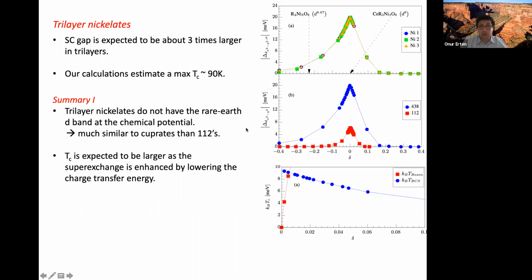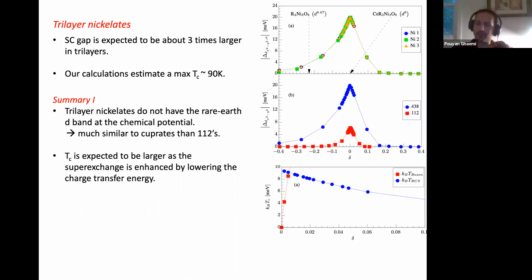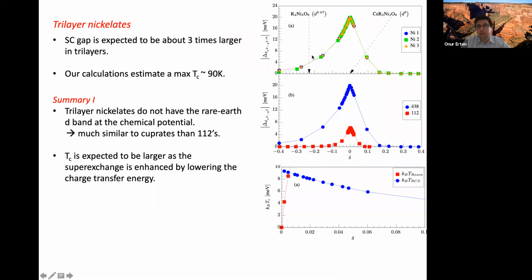Any questions? So the tight binding model, you directly do it for the 3-layer, right? Yes. Okay. Because I was thinking that if this is really getting to the cuprates, can you integrate out some bands and get an effective Hubbard model with the same number of orbitals, or not? Yeah, it is mainly, we still only have the nickel dx square minus y square orbital, but there are 3 of them. And that's actually important in the trilayer cuprates too, that leads to some bonding, anti-bonding orbitals. And leads to some different orbital occupancies. So here you can see these are the 3 different orbitals, and they have very similar gaps because the splitting between the bonding, anti-bonding bands is not that big.